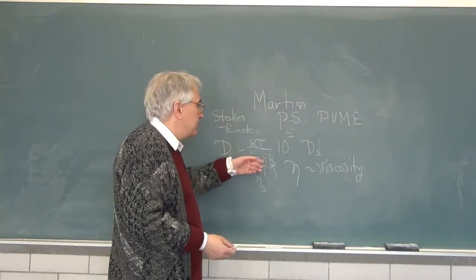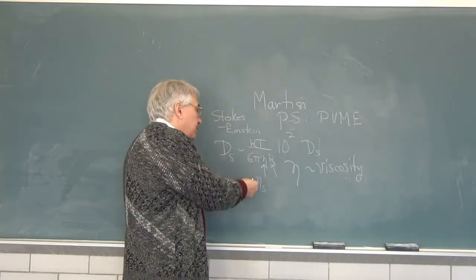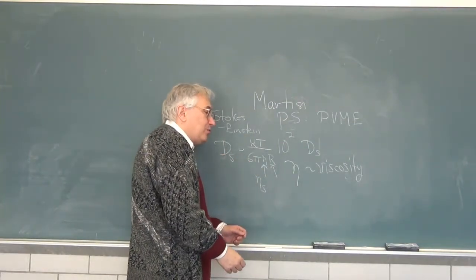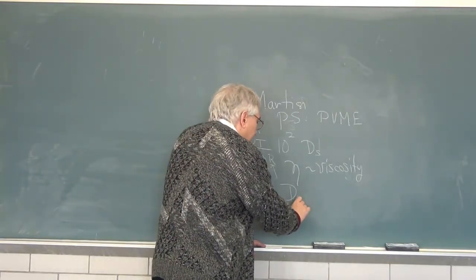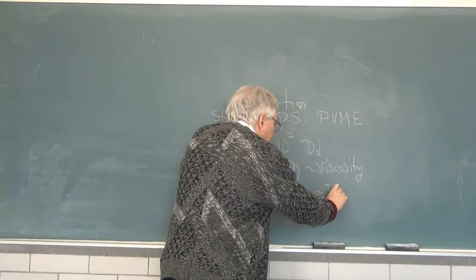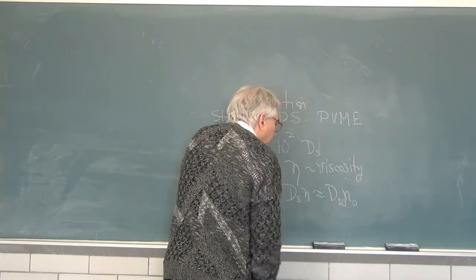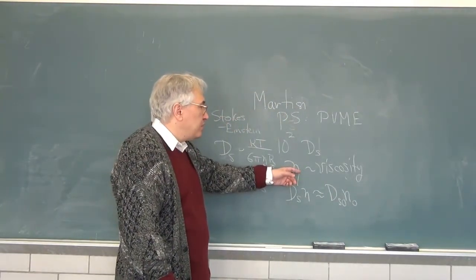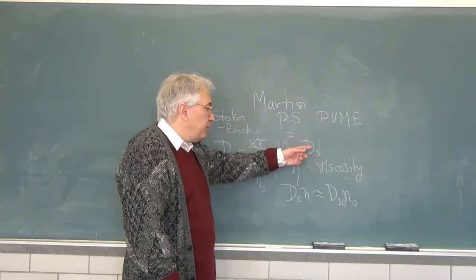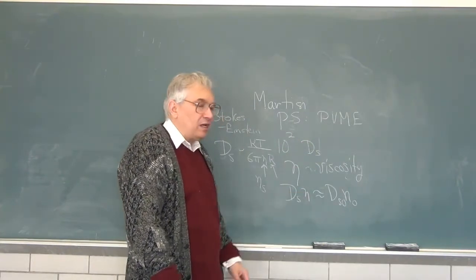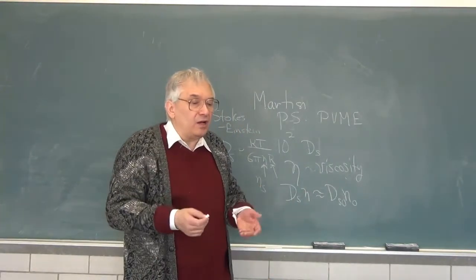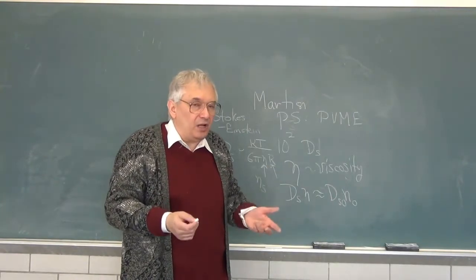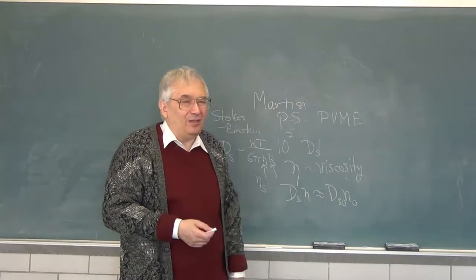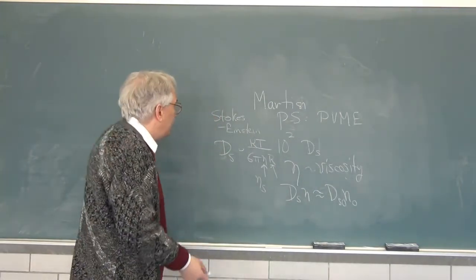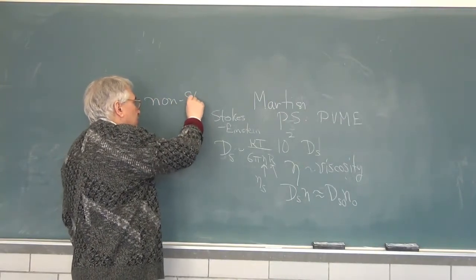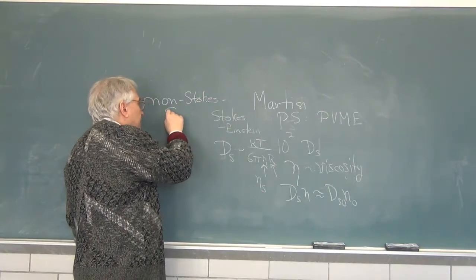However, if you believe you're looking at a system in which the Stokes-Einstein equation is right, or is approximately right, given that the probe polymers really aren't spheres, you would say that you would expect DS eta to be about the same as the value of the product in pure solvent. That is, as you add polymer to the system, the viscosity goes up, the self-diffusion coefficient goes down, and therefore you might expect, some people do, that the product ought to be fairly independent of polymer matrix concentration. Well, it really isn't. And you have non-Stokes-Einsteinian behavior